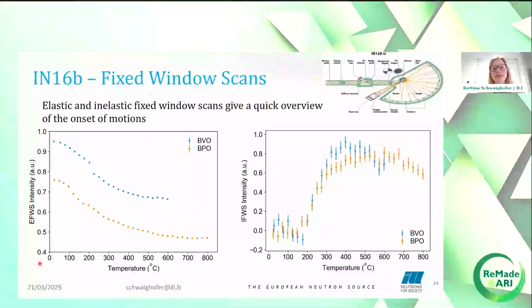First you measure elastic fixed window scans, which is just the Bragg intensity of the elastic peak at increasing temperature, and the inelastic fixed window scan, which is measured with a certain offset of the elastic peak. For us, it was 2 microelectron volts. And generally, you'd expect a sharp decrease of the elastic intensity at the same temperature as the inelastic intensity increases. Our elastic fixed window scans don't show a very clear, strong decrease as we expected, but the inelastic fixed window scans show clearly that at around 400 degrees Celsius, the QENS broadening should be strongest. We therefore measured both samples at 300, 400, and 500 degrees Celsius.